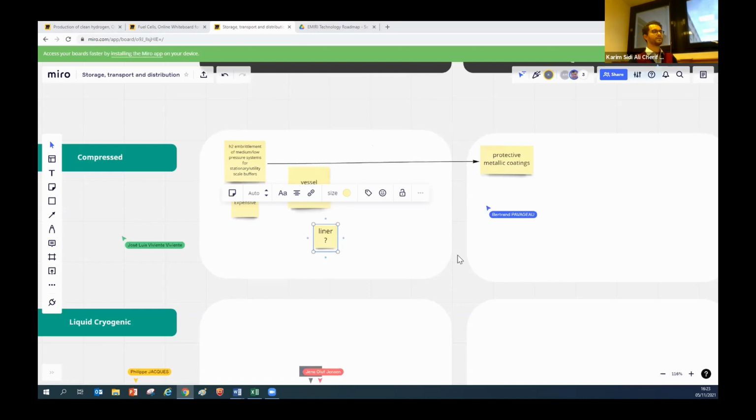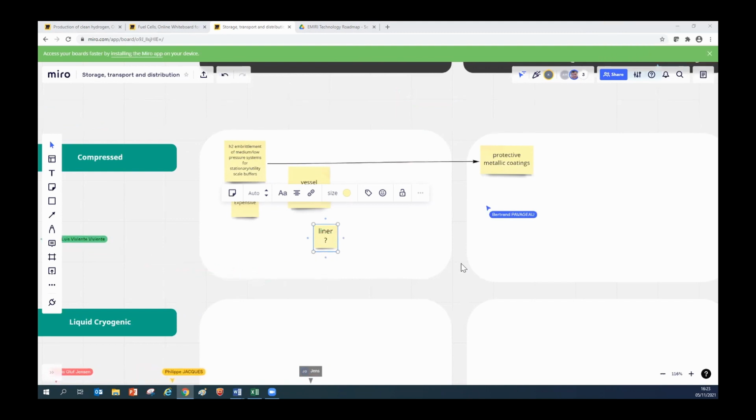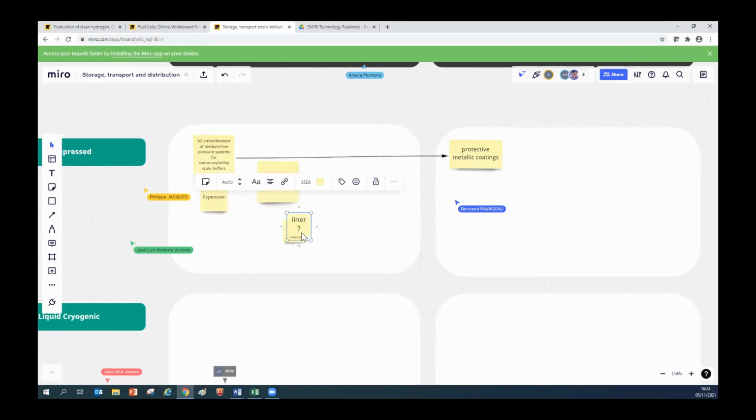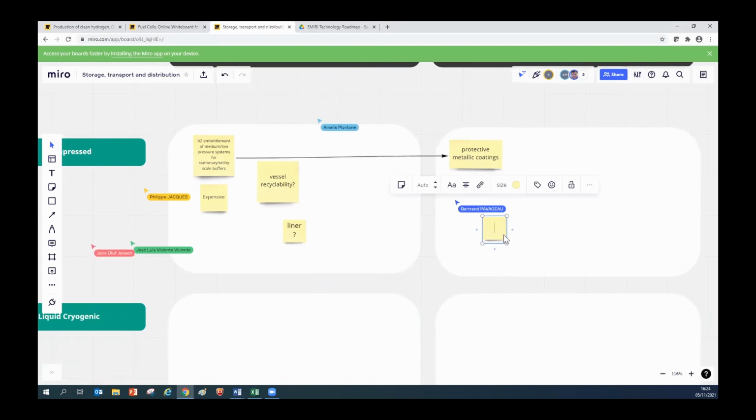This is Bertrand. Yes. I think right now, yeah. When you talk about this hydrogen permeation, are people thinking about making a liner that is the barrier, or making two different coatings? I don't know if you know the difference between Type 4 and Type 5 reservoir, but the idea is that in Type 5 you have a linerless solution. So that means the structural composite part also does the job as a hydrogen barrier. And that can be a way to avoid this liner presence and this liner issue, which usually suffers from compression, decompression, I would say the normal cycling life of this kind of reservoir. But we can also imagine having better adhesion between the liner and the structural part of the reservoir in order to avoid this liner collapsing issue.